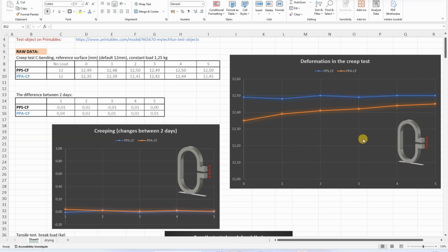On this graph you can see the directly measured values, distance between two reference surfaces, and yes, we can see more deformation on the PPA-CF, but the creeping is the difference between 2 days, which is basically zero in both cases, because these are very stiff, rigid materials and resist creeping well.